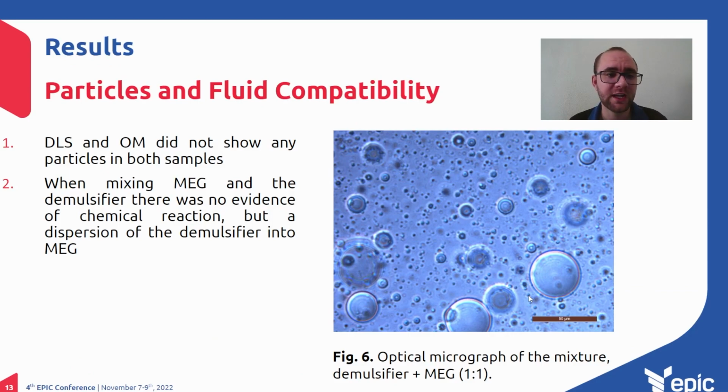For the particles in fluid, the DLS, dynamic light scattering, and the optical microscope didn't show any particles in both samples. We didn't see particles in the microscope. And when we mixed MEG and the demulsifier, there was no evidence of chemical reaction. We let them stay for a long time, and there was no reaction, only a dispersion of the demulsifier into the MEG. So only one fluid dispersed in the other, not a reaction, not the formation of solid particles.